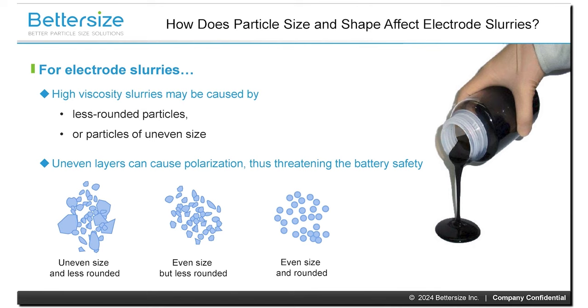One key to battery production lies in the consistency of the electrode slurry, where control of the density and viscosity is vital. Particle size and shape affect slurries' rheological properties. Generally, smaller sized particles typically lead to lower viscosity slurries, and irregular shapes can result in higher viscosity slurries. In terms of coating uniformity, small sized particles produce uniform coatings, which result in electrodes' consistent thickness and electrochemical performance, and spherical shaped particles tend to pack more densely and uniformly.